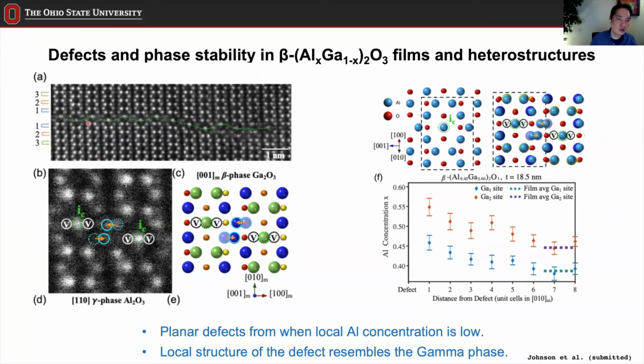So this again relates to the secondary relaxation that I showed you earlier, right? So when the aluminum concentration is locally low during the growth, it actually relaxes in a way that resembles the gamma phase, although this is not a complete phase transformation. The structure becomes more like the gamma phase. But then after that, if the condition improves and gallium deficiency is resolved, then the structure recovers to the monoclinic structure. Okay, but that's in case of lower aluminum concentration.